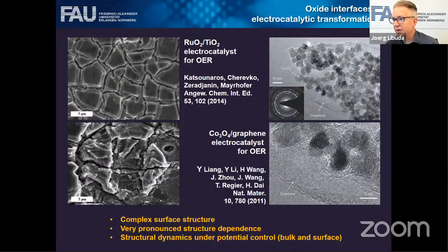There's one thing on top with oxides. Oxides very often show a very pronounced structure dependence. In sharp contrast to metal surfaces or many semiconductors, the reactivity of an oxide surface is completely different, whether you look at one facet or another. I will show an example. So there's no way around really knowing what the structure is for the particular system that you look at. That's a very big difference to other systems.